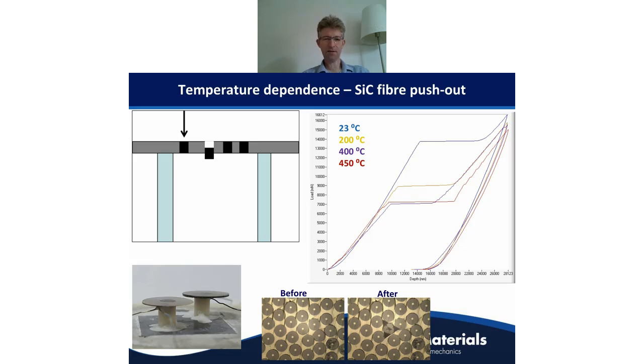We can also do these types of tests under more extreme environments. In this case, this is for another aerospace application. This is now silicon carbide fibers in a silicon carbide silicon matrix composite, and this is now at much, much higher temperatures. Also these loads are higher, so in this case we use the high load head in the system. We can see that these push-out forces are very temperature sensitive. So this again shows the importance of being able to test under the relevant environmental conditions.